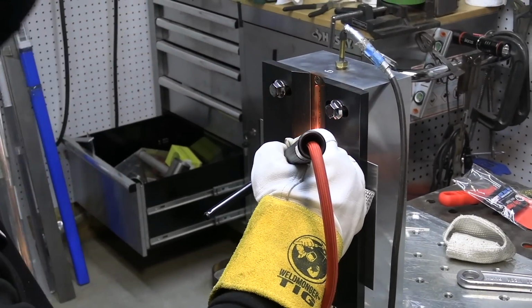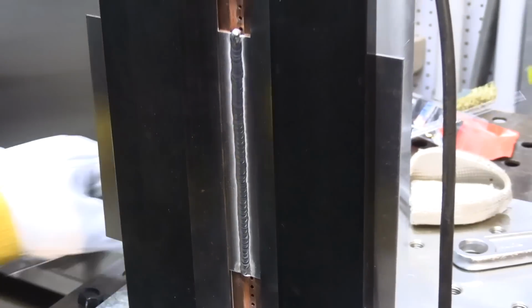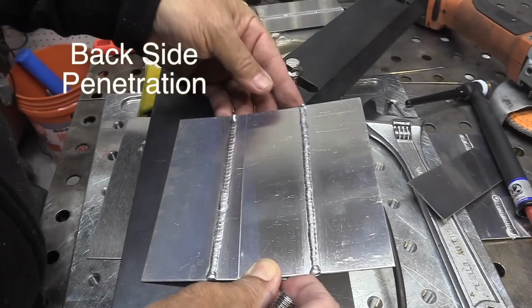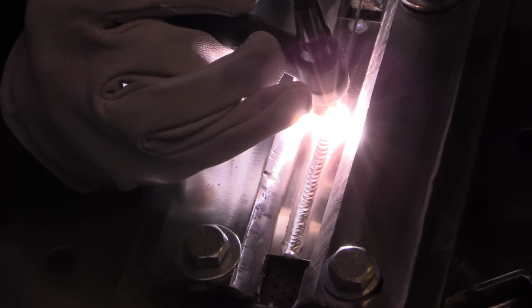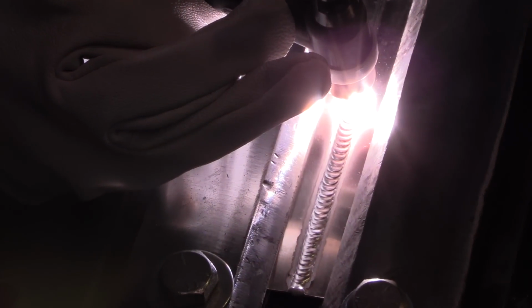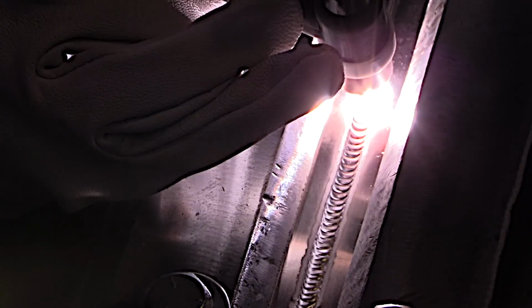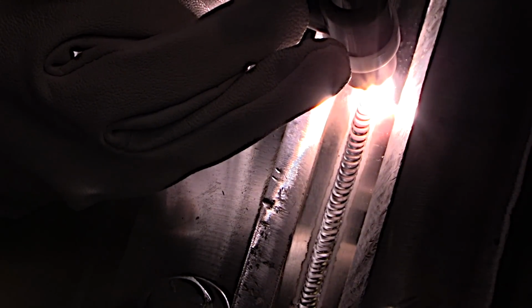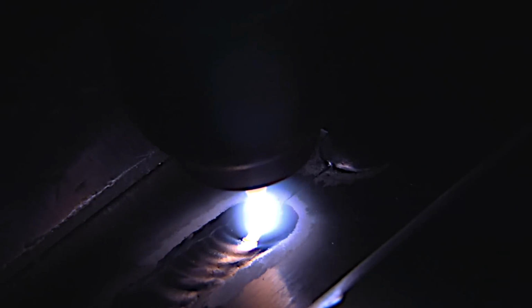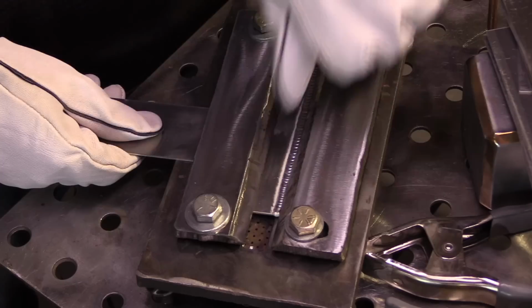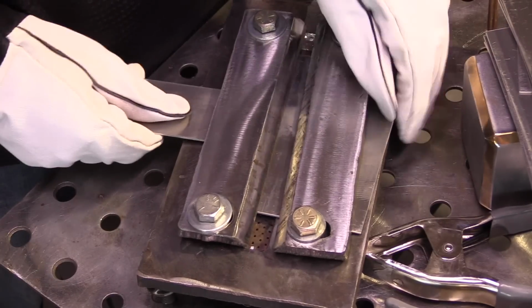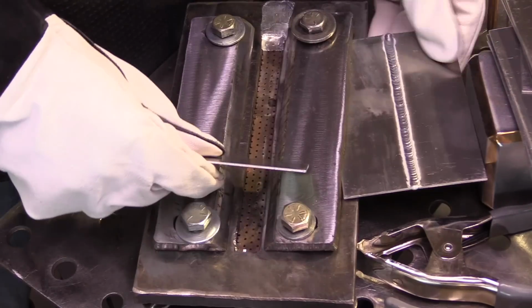If you do have a test coming up like this in your future, these next few seconds should be very valuable to you. A full penetration butt joint like the one you see here is most often tested using X-ray. And porosity is by far the most common reason for failure. Porosity is caused by trapped gas, and that could be from oxides, it could be from hydrocarbons, it could be from impurities in the sheared edge.